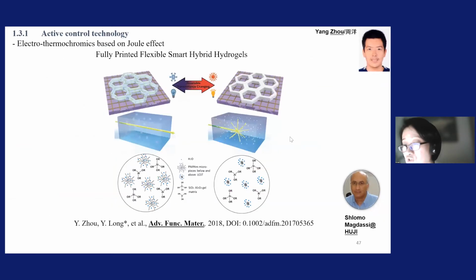Okay, and then we continue to work on it, because we want to make it more or less printable. We're not only satisfied with this hydrogel printed on the transparent electrode, we hybridize them, because hydrogel is an organic gel, right? It's a water-based organic gel. Then we hybridize it with silica aluminum gel, which is more or less like a silica gel. We borrow the strength of this silicon aluminum gel, so this hydrogel can solve the problem of its fragile characteristic, make it printable, and at the same time maintain its smart functionalities.